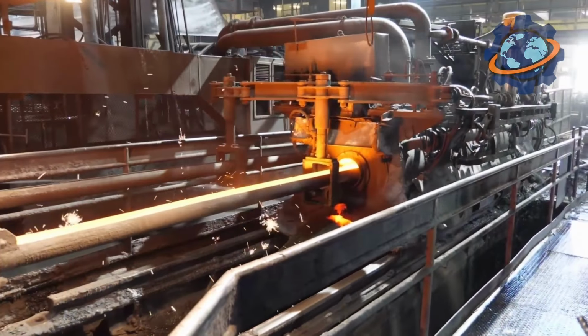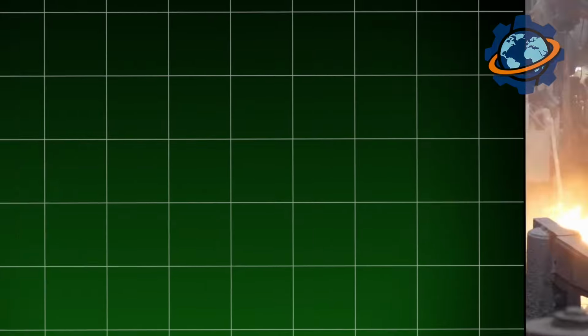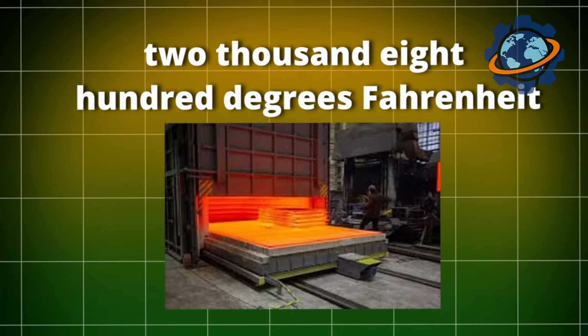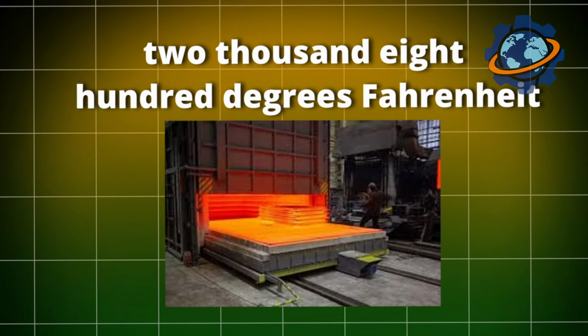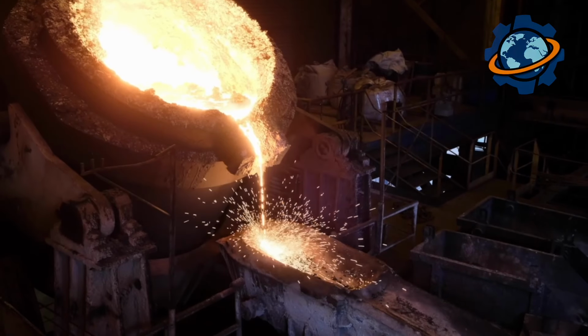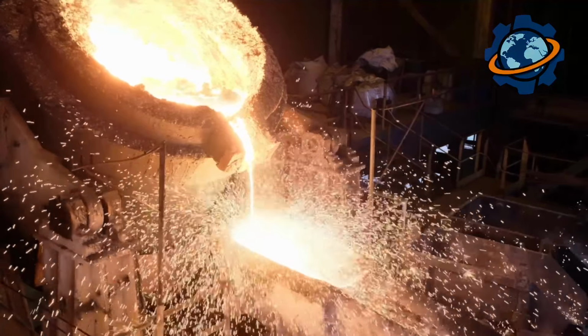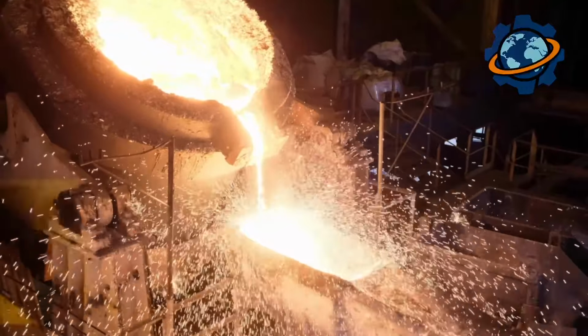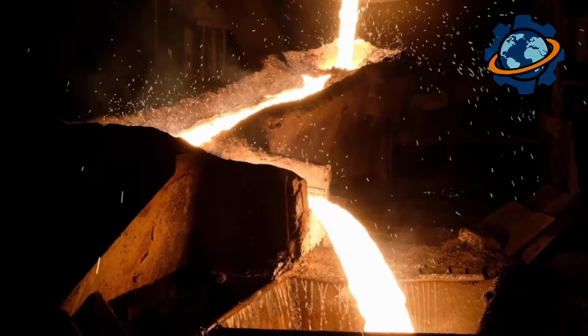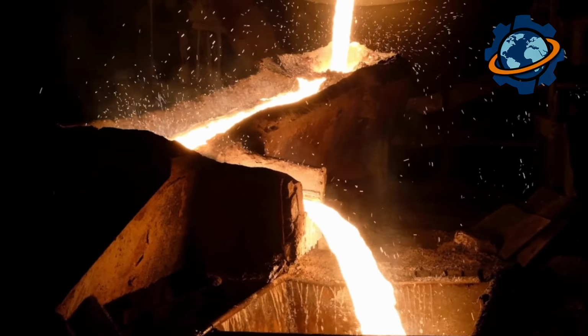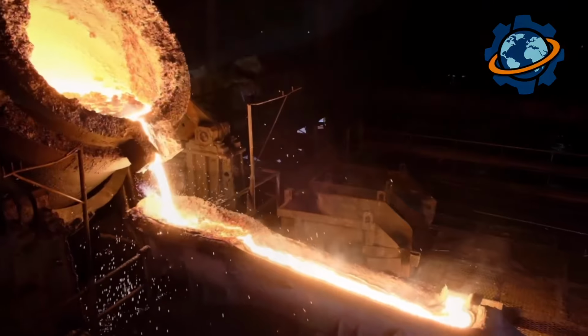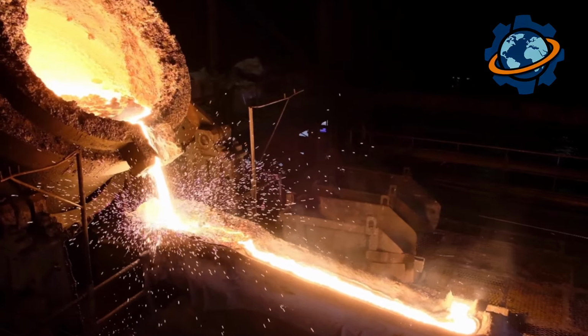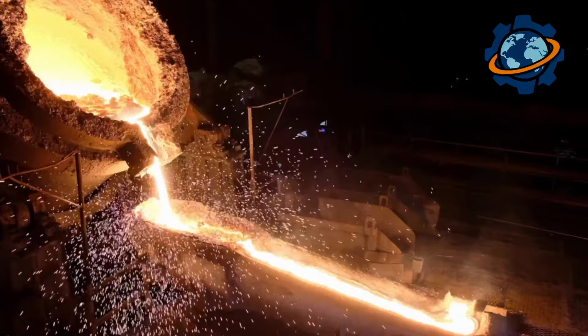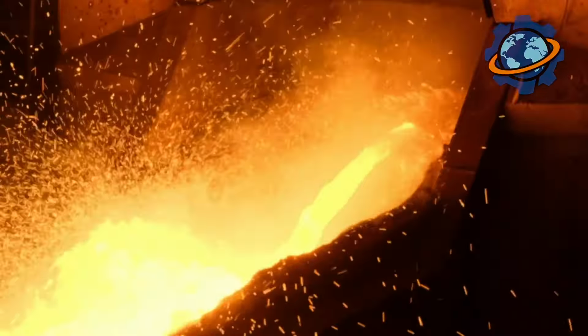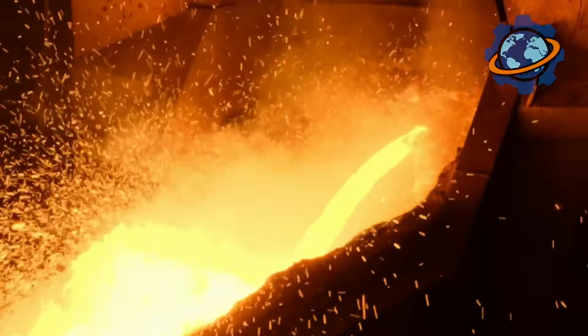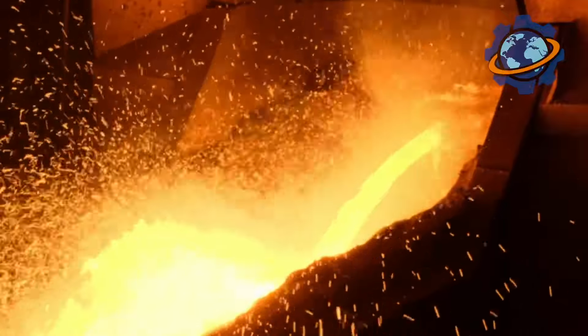At the hearth bottom, molten iron collects at 2,800 degrees Fahrenheit, dense as lead but flowing like water. Every 4 hours, workers drill through clay-plugged tap holes. Liquid iron erupts in blinding white rivers, flowing through ceramic channels into railroad cars holding 300 tons each. This step is critical because timing determines metal purity. Tap too early, slag contaminates. Too late, furnace pressure ruptures containment walls.